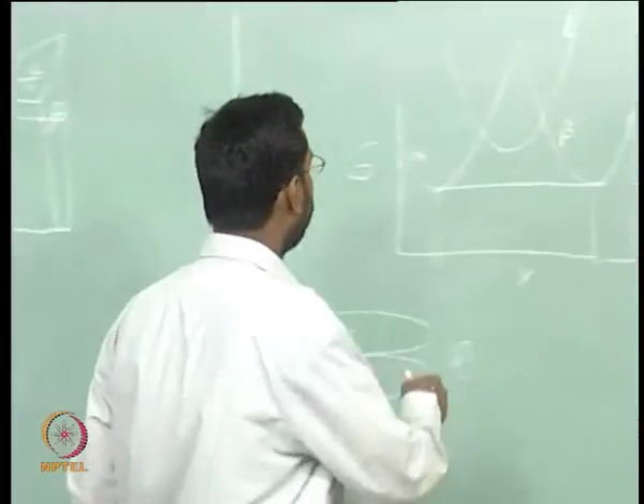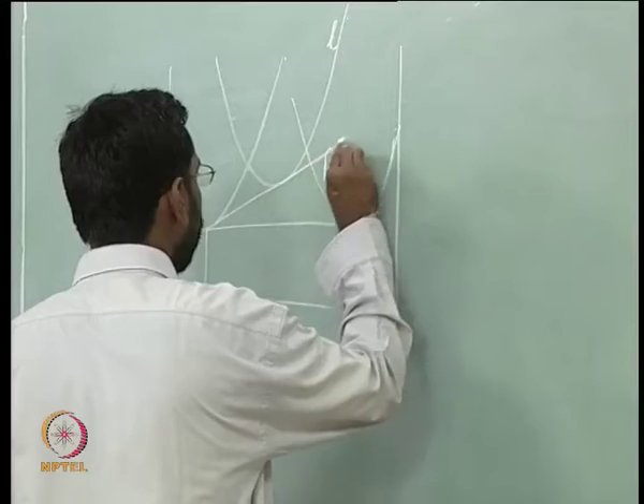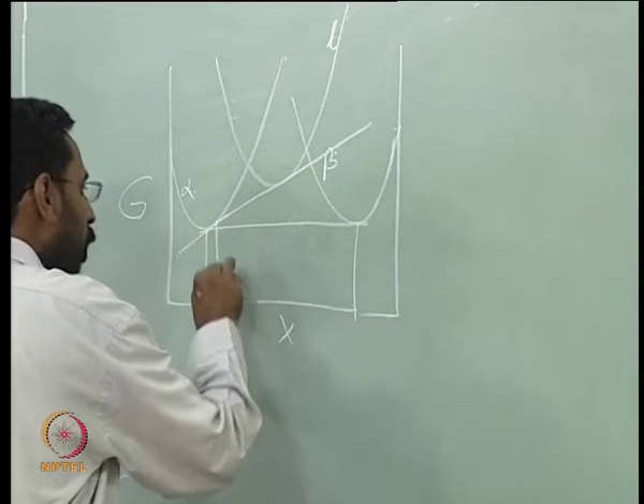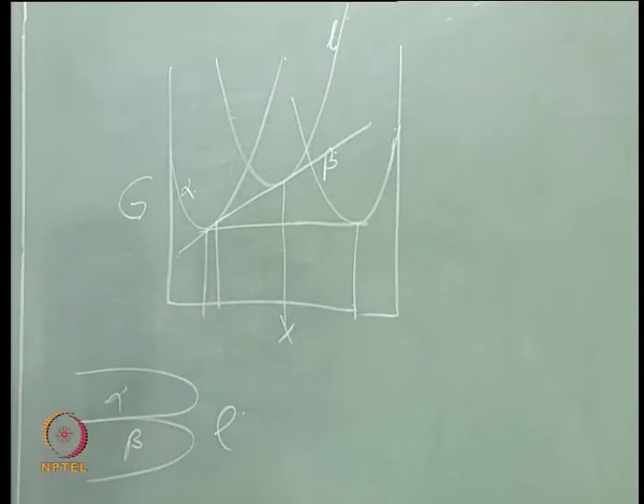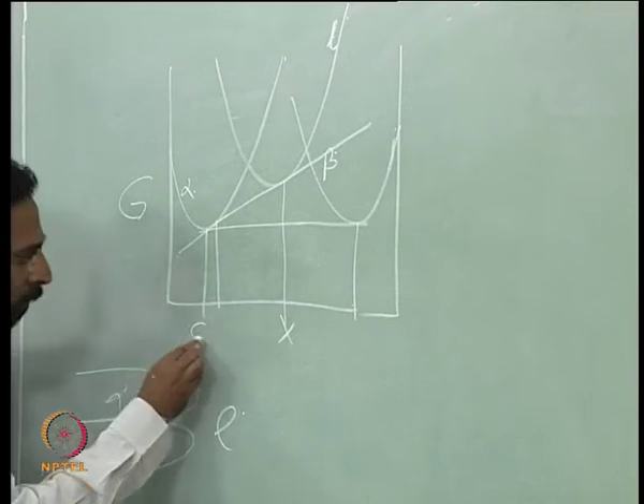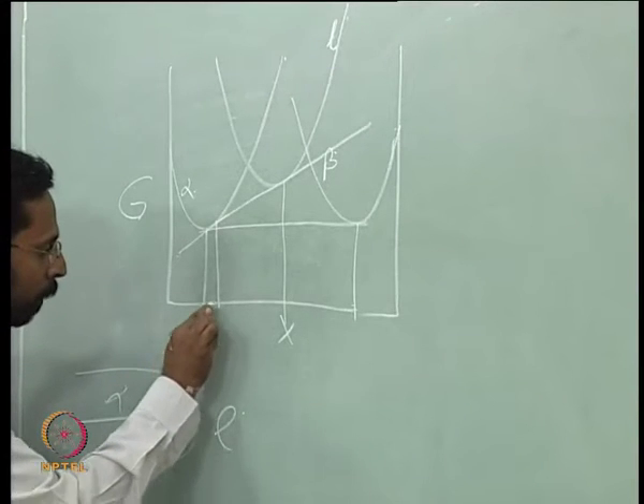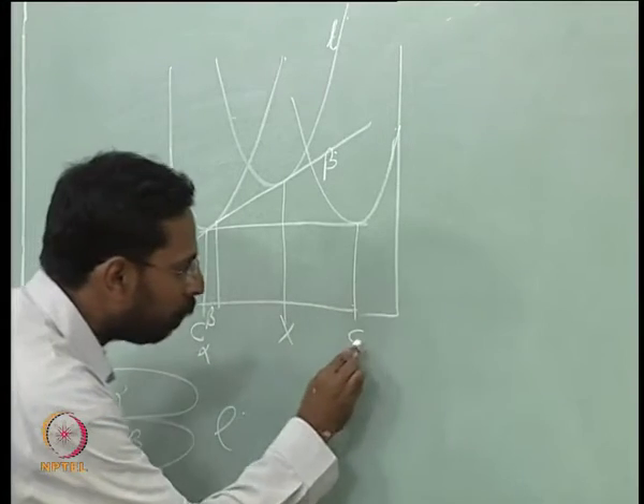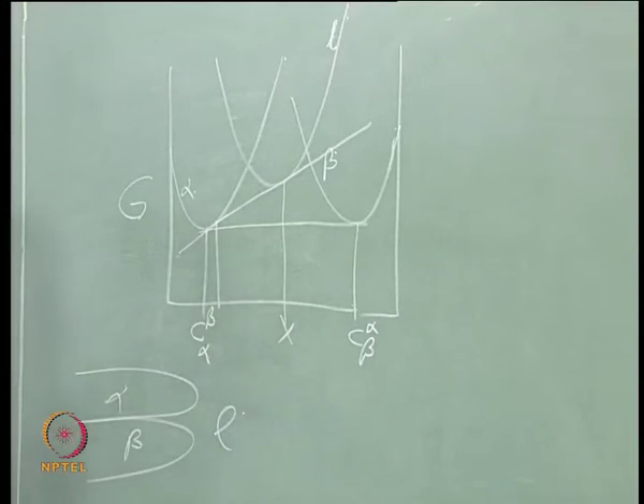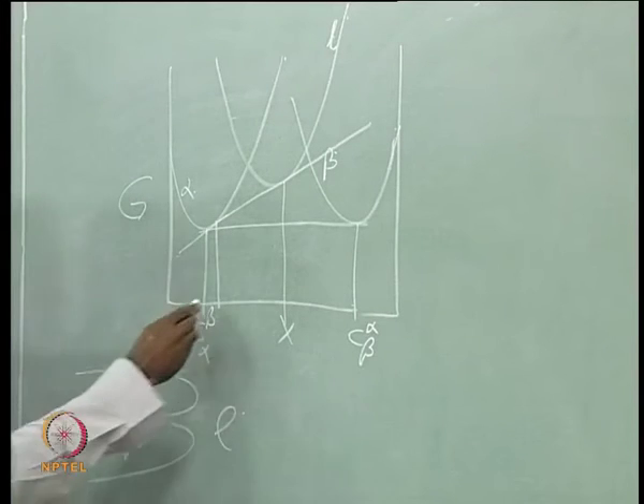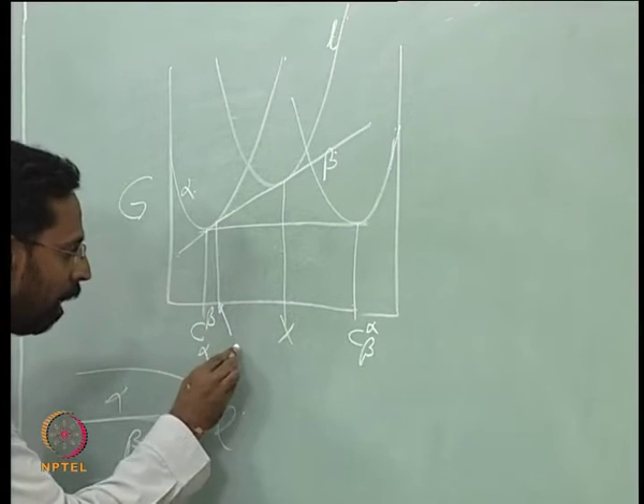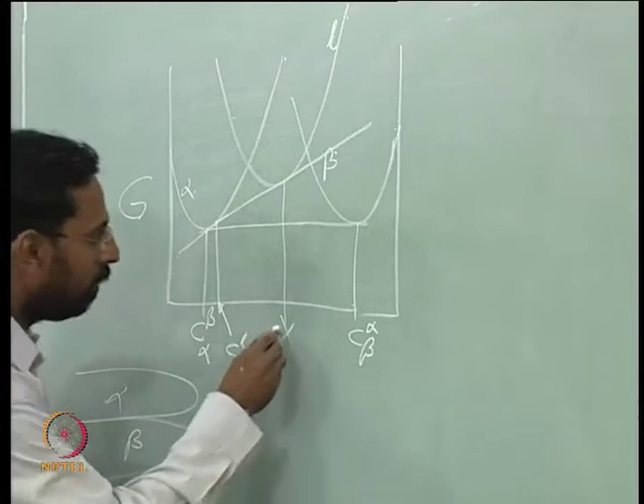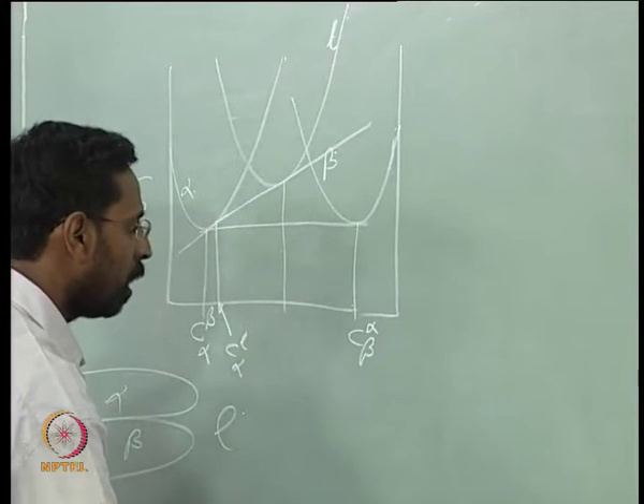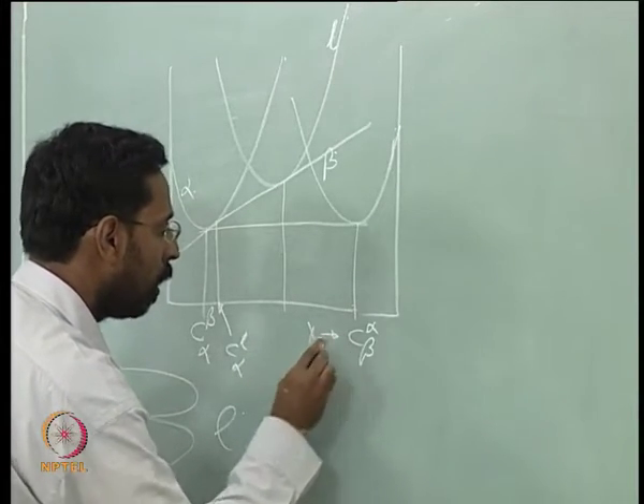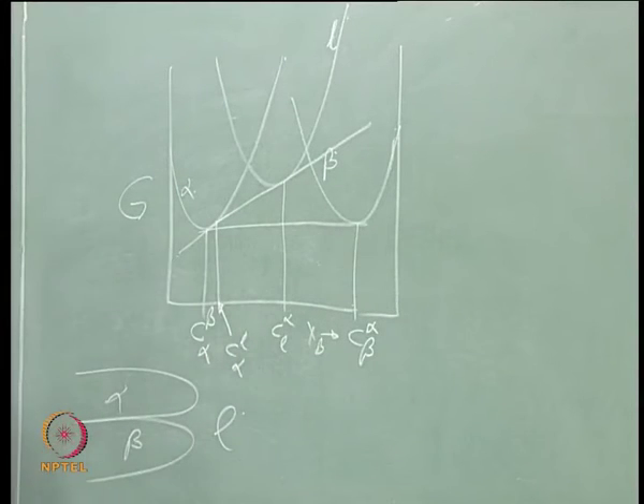So when I say equilibrium between alpha and liquid, I should draw a common tangent between alpha and liquid. How do I draw that? Something like this. So you have this composition and this composition—let us give notation for the first two compositions we already drew. This is the composition of alpha in equilibrium with beta, and this is the composition of beta in equilibrium with alpha. And what is this composition now? C-alpha-liquid, and this is C-liquid, this is C-liquid-alpha.